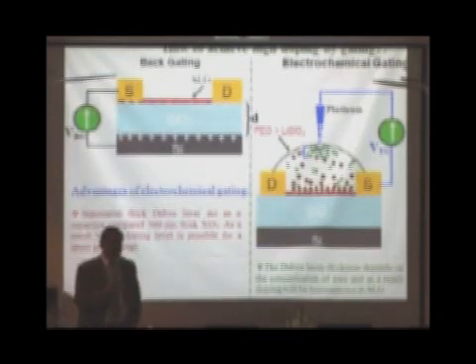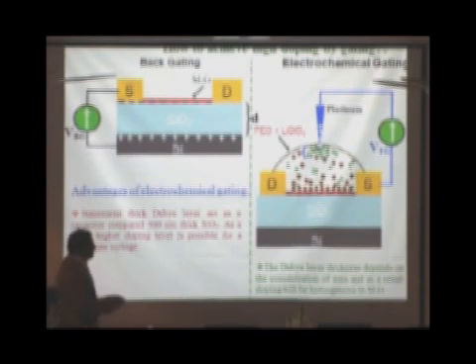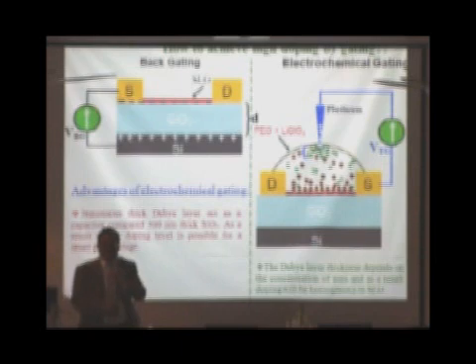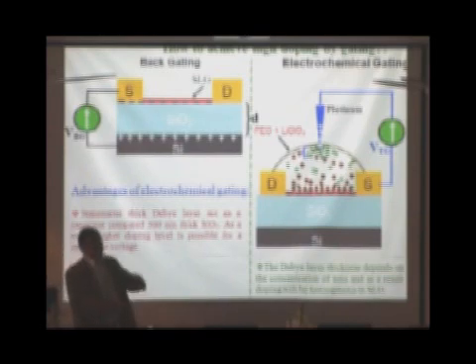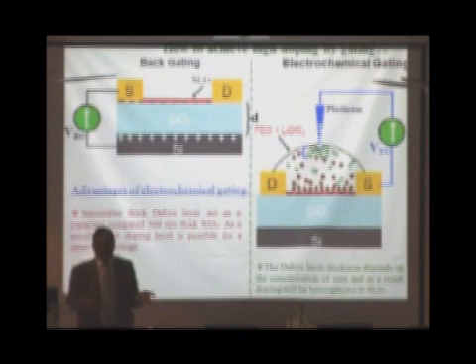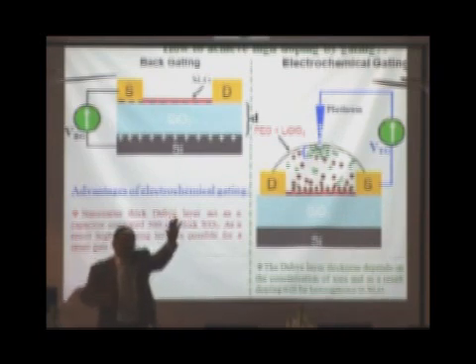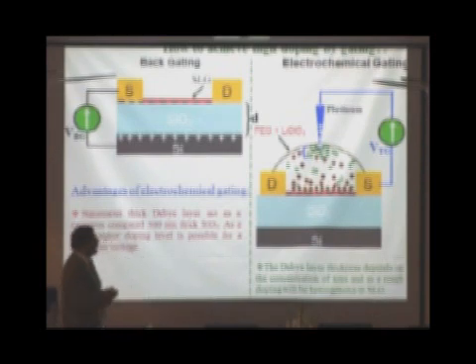What we have done is a small trick. Instead of using 300 nanometers of gate oxide, we put a drop of solid electrolyte — a polymer with lithium perchlorate. When you apply a gate voltage via a platinum or gold wire, you form a Debye layer near the graphene — ions come nearby. The Debye layer thickness is about one nanometer. So instead of 300 nanometer gate oxide, you have one nanometer. Whatever you could do with 100 volts, you can now do with less than a volt, enabling very large doping of the graphene. This electrochemical doping allows very large doping with very small voltages.